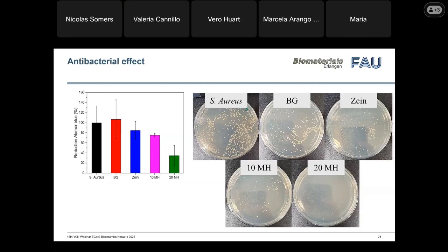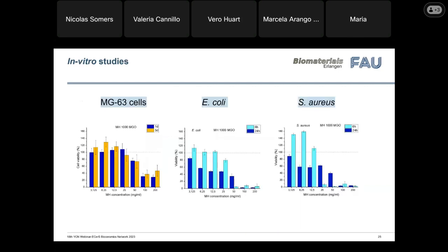Here I just showed the results of the antibacterial studies using metabolic test and also colony counting, and we can clearly observe a reduction of bacteria, especially at the highest concentration of honey. So this was quite positive for us that we could see this effect here. But then we kept